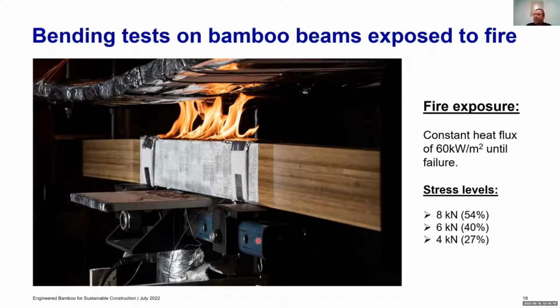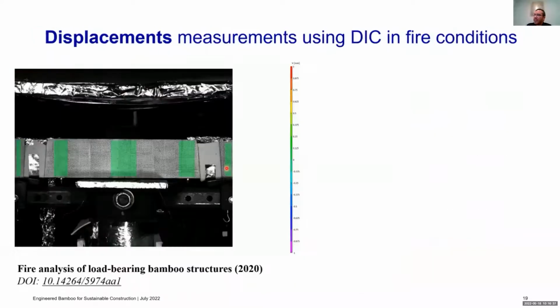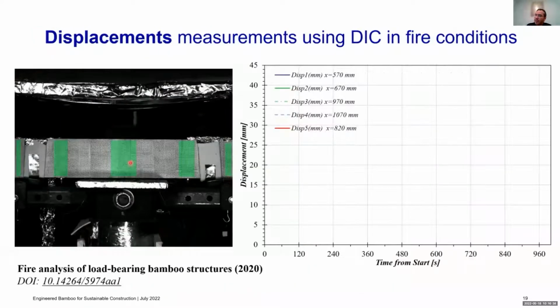This is not an easy test. We couldn't make it at the structures lab at the university because of all the challenges that fire brings. So we did it at the fire lab, and I ended up designing a machine that allows us to do this test. And what you see here is that I painted the surface of my bamboo sample to be able to use a digital image correlation analysis.